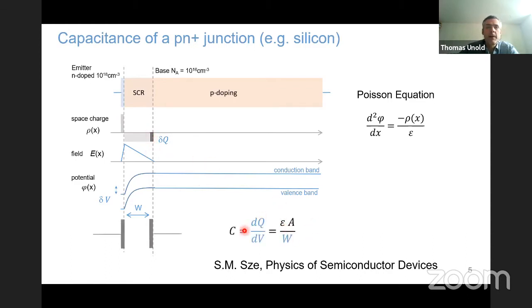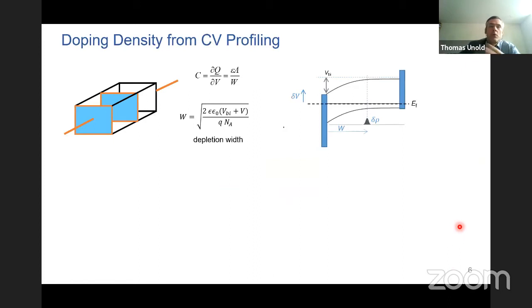And now the capacitance is actually simply given by delta Q over delta V. So the charge that comes out here when you change the voltage a little bit, and that is in this most simple picture actually given by the dielectric constant times the area of the device over the depletion width here. And so let me go a little bit further into this, and I magnify now the depletion width here. So here you could actually think of this as a flat plate capacitor, right? So here's one plate and here's the other plate.